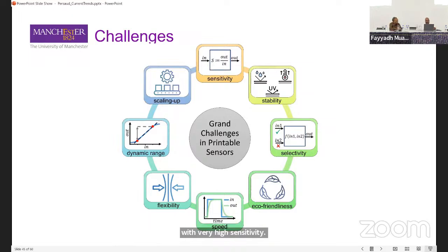So metal oxide semiconductors normally are heated. If you heat a metal oxide, like tin oxide or tungsten oxide, to about 300 degrees, they turn into semiconductors. You have a thin layer of oxygen adsorbed on the surface. And molecules like benzene, aromatic compounds, will displace oxygen on the surface, and you can see a very big change in conductance. Now, organic conducting polymers are more polar. So they have a big electric field over their surface, so they are not very sensitive to aromatic compounds.